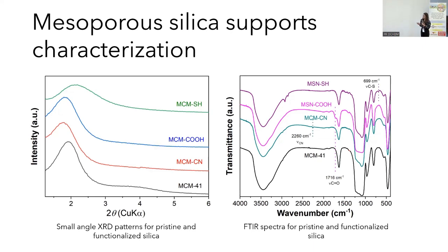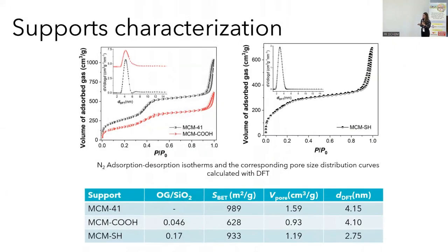You can also note the 100 Bragg reflection that is present for all the samples. The FTIR spectra for pristine and functionalized silica revealed, besides the bands specific for the silica matrix, the bands specific for the organic moieties, of course, for the functionalized ones. You can note the specific vibration of the cyano group, the carbonyl group, and others. The nitrogen adsorption-desorption isotherms recorded at 77 Kelvin were all type 4 isotherms characteristic for mesoporous materials. You can also note the textural parameters that are high, specific for those kind of materials, but somehow lower for the functionalized ones due to the presence of the organic moieties on the inner walls of the pores.